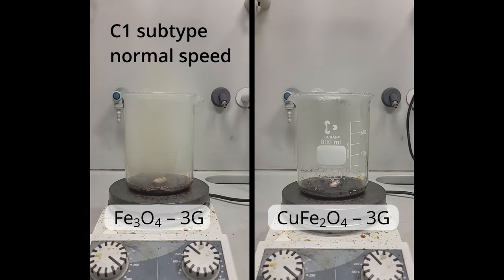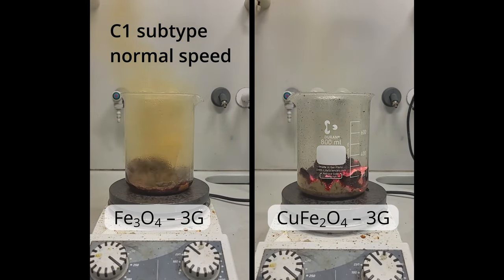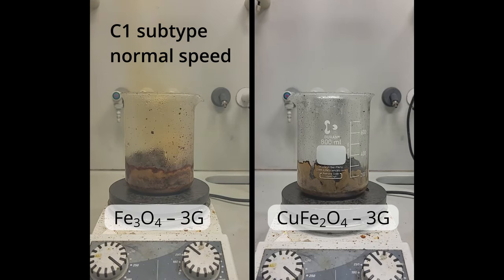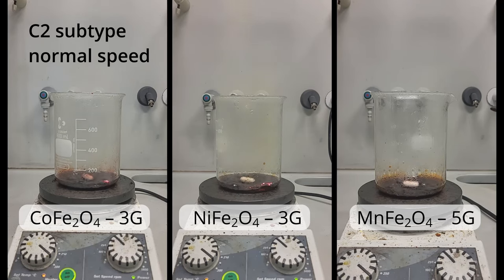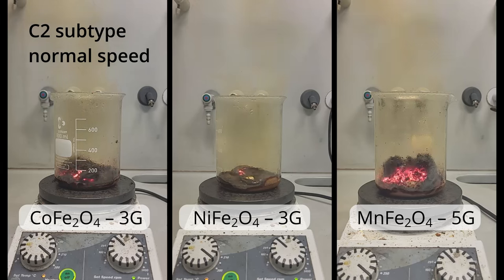Finally, type C is called the foam. Note the structure that appears to grow out of the combustion container. In the C1 subtype combustion, we form a low density pumice-like material. Finally, the C2 subtype includes the most spectacular combustion, which is the formation of a foamy column of matter that rises from the bottom.